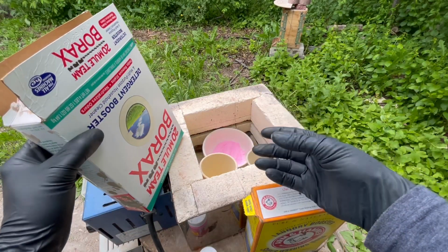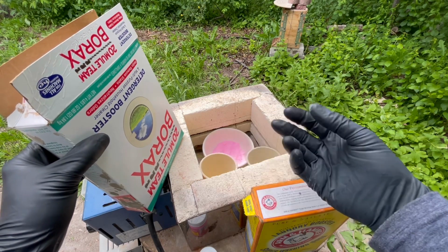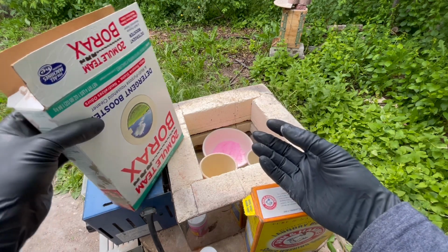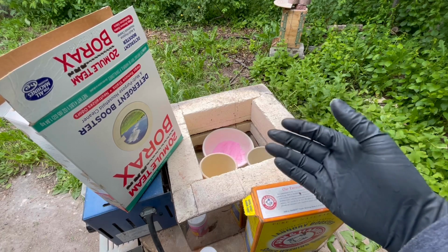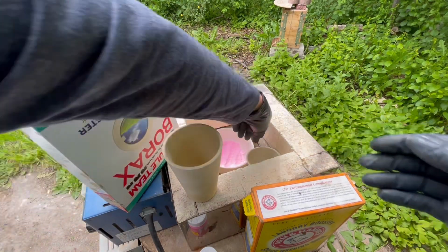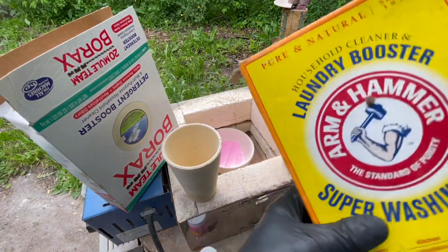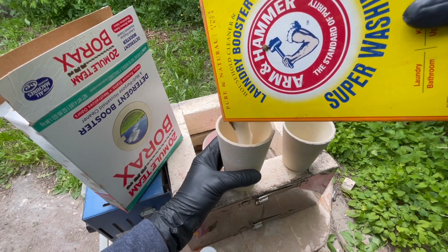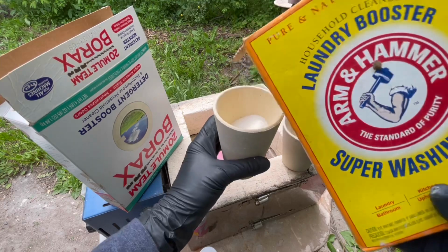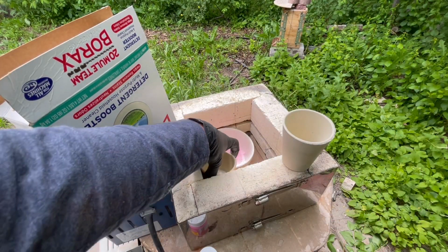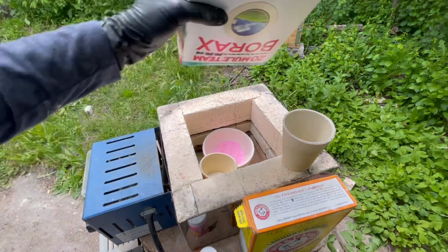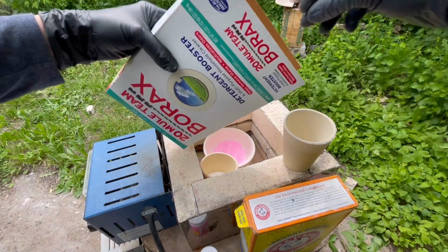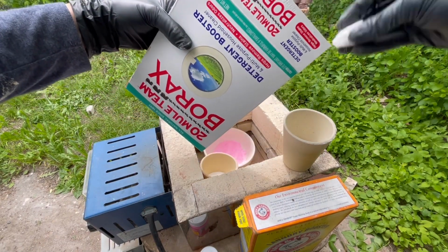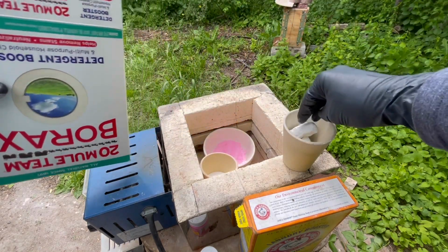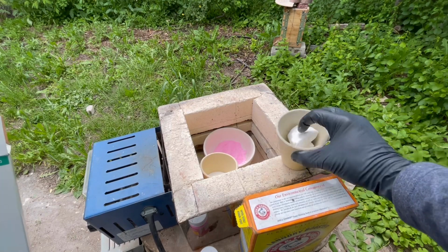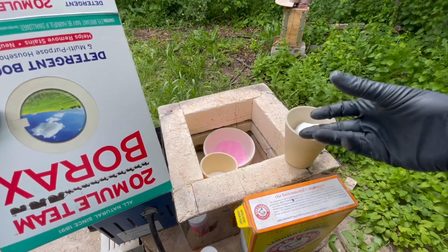And just like the carbonate sample that we had, that water and carbon dioxide, if it bubbles out during the assay process, is going to cause the sample to boil over and you're going to lose it. So I'm going to preempt that by heating the washing soda and borax up to about 600 degrees Celsius to remove all the water and carbon dioxide. I don't really want to fill the crucibles all the way up because the borax especially is going to expand as it cooks.